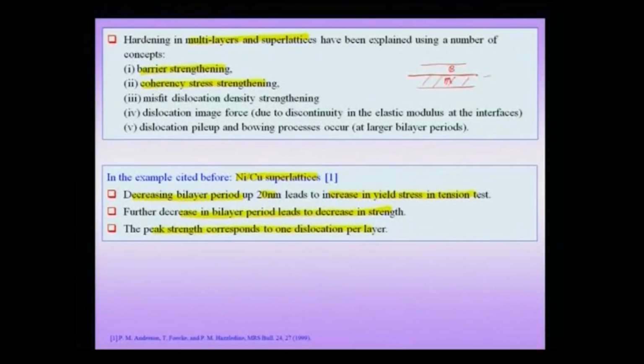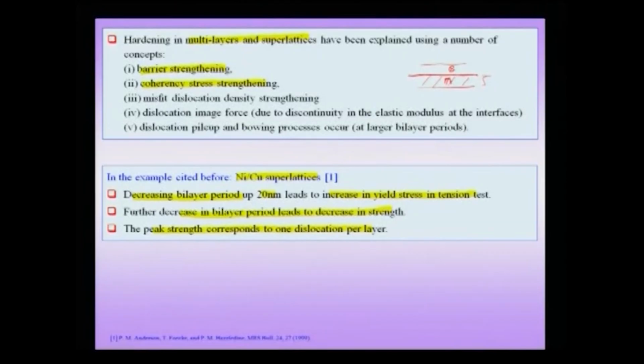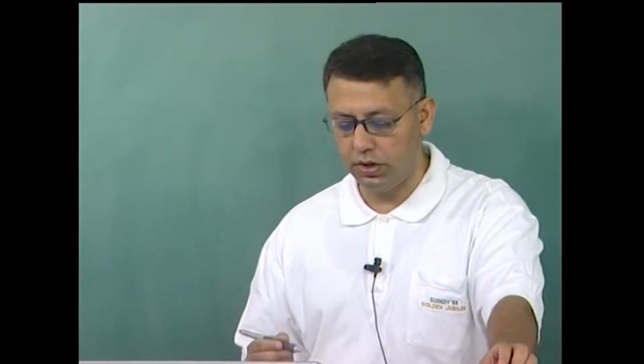It is also assumed that if this bilayer period becomes large, and if you start with what you might call a coherent system, then it will no longer remain coherent for large thickness, and in fact you may obtain misfit dislocations decorating the interface. So typically you could have certain decoration of misfit dislocations along the interfaces, which implies that the system is partially coherent, and this misfit dislocation would impede the motion, and this misfit dislocation, as we have noted before, is a structural dislocation.